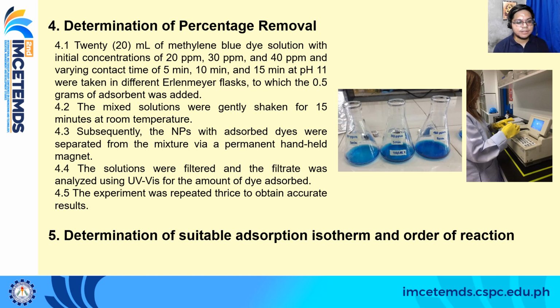And lastly, for our methodology is to determine the suitable model for adsorption isotherm and the kinetics of adsorption. For the isotherm, we used two models, which are the Langmuir and Freundlich models, and tested if our data would suit either of the two. And for the kinetics of adsorption, particularly the order of reaction, we had three models: the pseudo first order model, pseudo second order model, and we also used the simple Lagergren model.